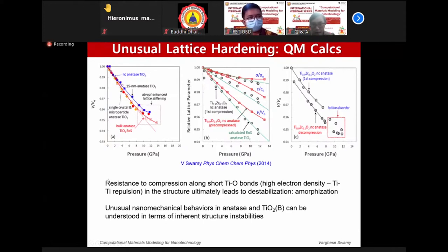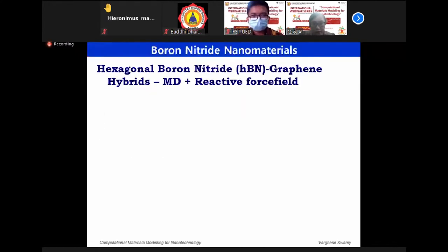So just to summarize, resistance to compression along the bond, short bond lengths because of the electron density increase, is ultimately what's causing the destabilization of the structure and amorphization. So that's what we can learn from this exercise. Now I'll stop with the titania TiO2 calculations.